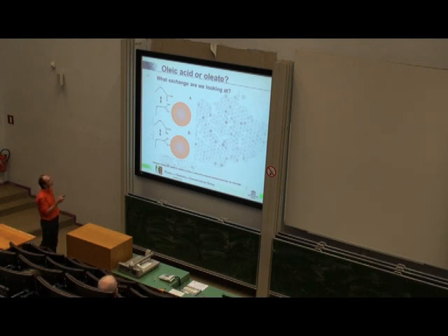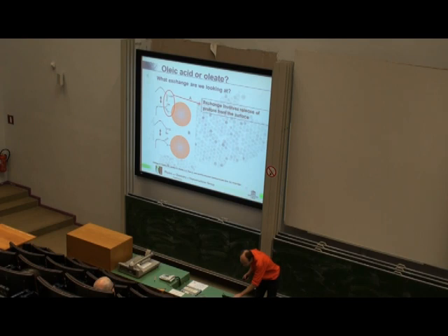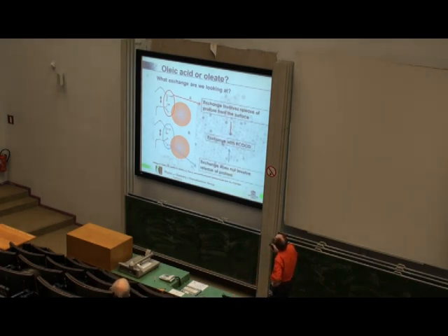If you think in terms of this exchange, if you have this excess acid there and you exchange it with one that is originally bound, then you will recover protons that were initially next to the surface, you will recover them in solution. In this situation, you will not get any protons from the surface. And we can tell the difference between both by doing this exchange not with protonated acids, but with deuterated acids. The point is, you don't see deuterium in the NMR spectrum. So if we don't have protons present on the surface, that's the first scenario, we will also not see them after the exchange. While if we have protons present on the surface, they will appear after the exchange.